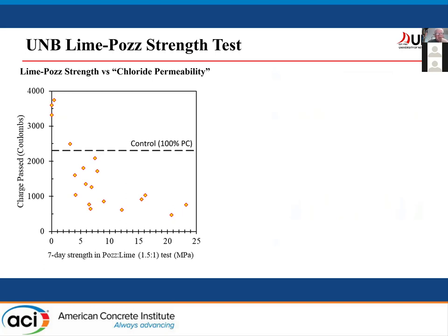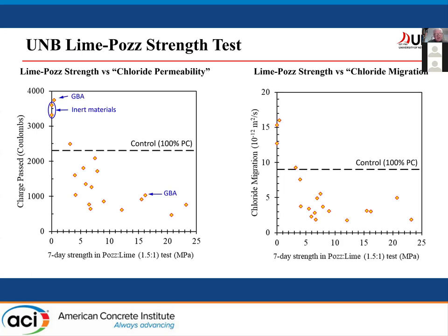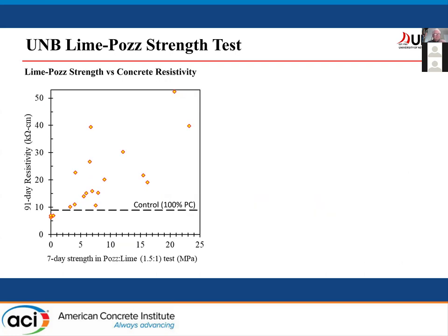And this just shows that the ones with good 7-day lime pozzolan values have low charge passed in the Coulomb test, the ASTM 1202. So the reactive materials, including the ground bottom ash, have low Coulombs and high strength in the 7-day test. And the same with the chloride migration, the 492 test. When it's ground, we get good values when you get sufficient material in there. And the same with resistivity.